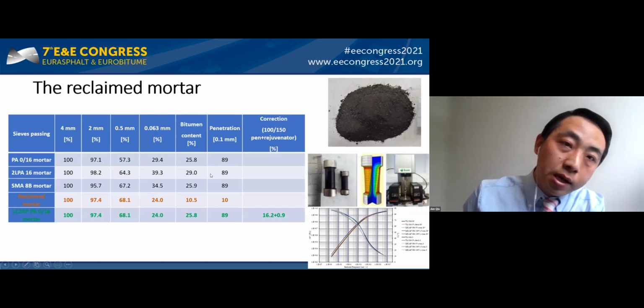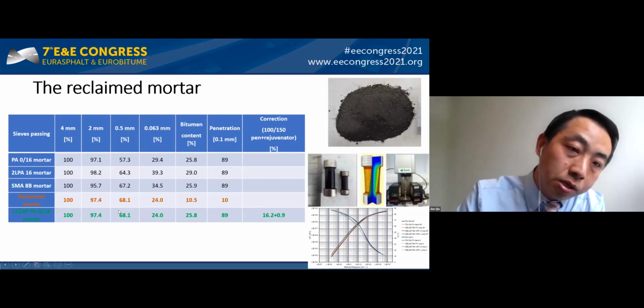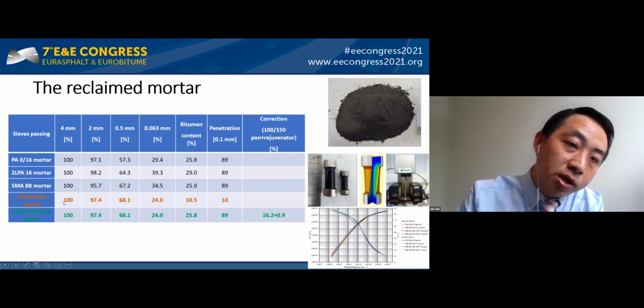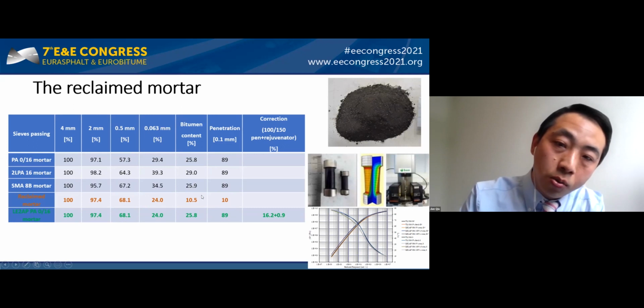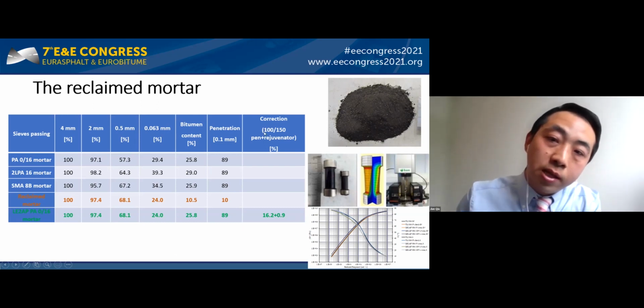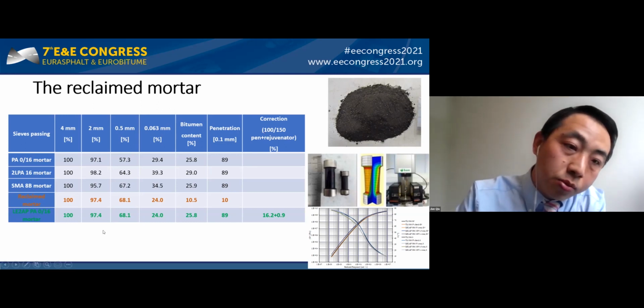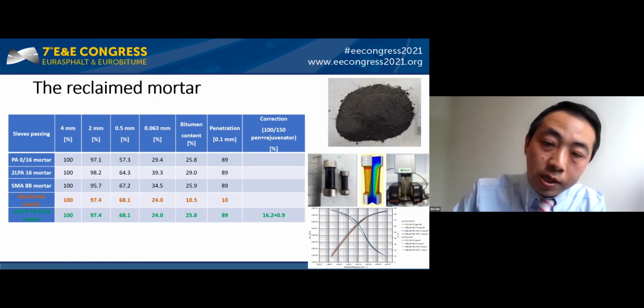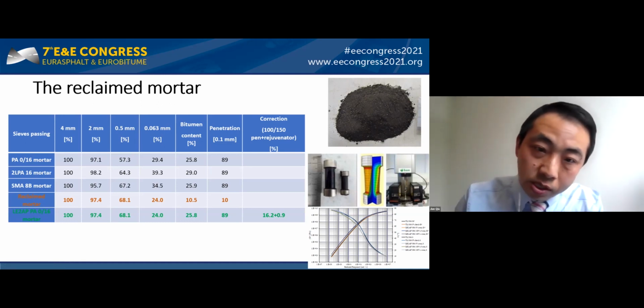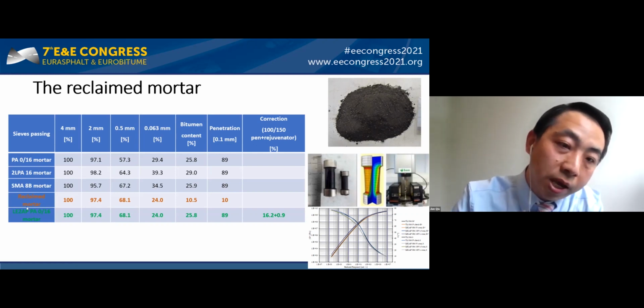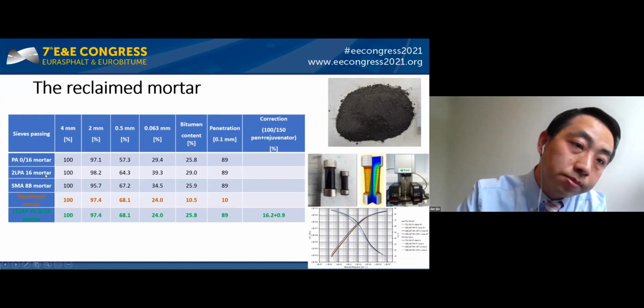The mortar that you get has almost similar gradations in the sand and fillers compared with the virgin mortar, but it has a low bitumen content and also a lower penetration. So we have developed a blending rule to enrich and rejuvenate it by addition of softer bitumen and also rejuvenator. Afterwards, when you get a mortar, you are able to test it at laboratory scale with the DSR. So we are able to make a high quality mortar compared with the virgin.